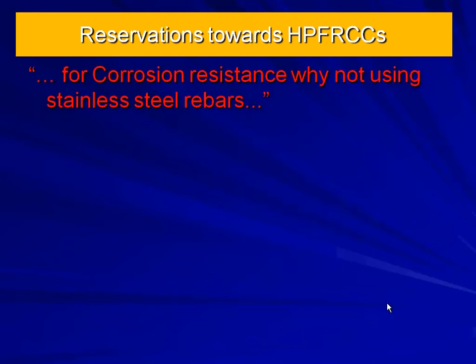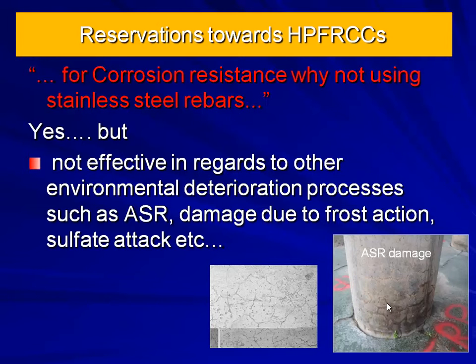Now, the question here I hear very often, for corrosion resistance, why not use stainless steel bar? Perfect, of course. But the issue here is more than that. You have not only the structural corrosion, you have all the other deterioration processes as well. So you're singling out one, whereas you still have alkali-silica reaction, as you see here, you have all the drying shrinkage cracks and so on. So just focusing on one area is not sufficient. Most of these structures are exposed to many of the deterioration processes, not only one. So only targeting one is not sufficient.